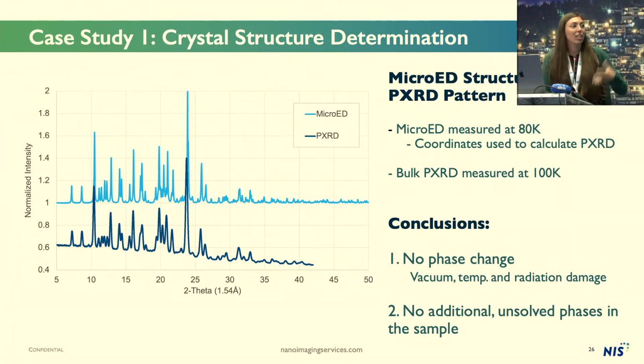Another nice thing that I can share with this compound is that we also measured the bulk powder diffraction pattern from this sample, which is the dark blue line here, and compared it with our microED-generated, simulated powder diffraction. And you can see that these two spectra line up quite well. There's a little bit of shifting in the peaks of the two patterns, which we speculate is probably mostly due to thermal effects. We do our microED measurements at 80 Kelvin, and the powder diffraction was measured at 100 Kelvin, so there will be unit cell expansion and contraction with temperature changes, which is probably where the differences come from.